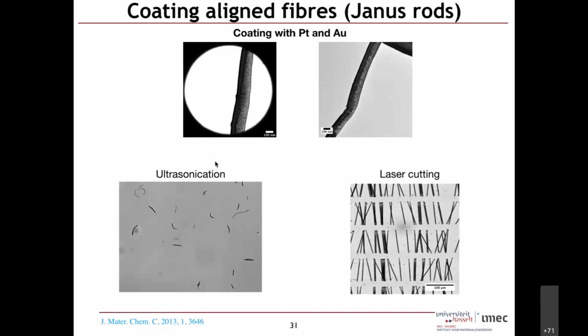Now we have made the fibers and coated both sides. Now we need to break them. We can do two kinds of things. You just take these fibers, put them in a sonication bath, and break them randomly. One advantage is you get all kinds of sizes of fibers. So in one experiment, you can do a lot of data collection because of the different sizes of particles, but there is no one size that you can repeat.